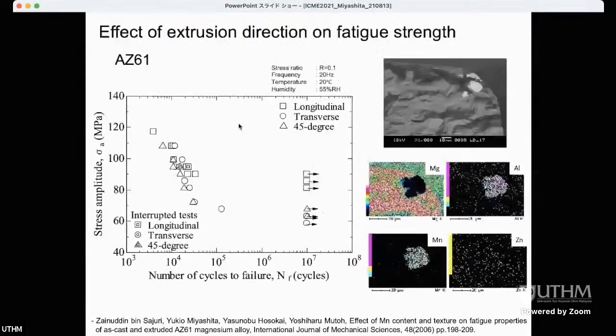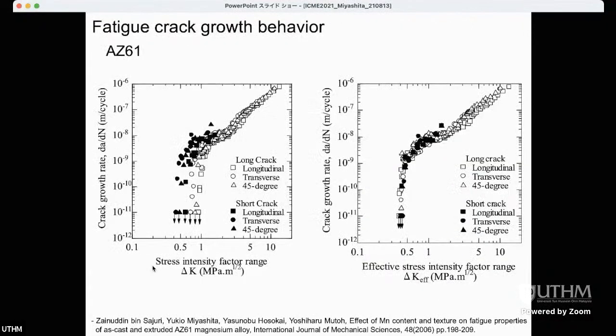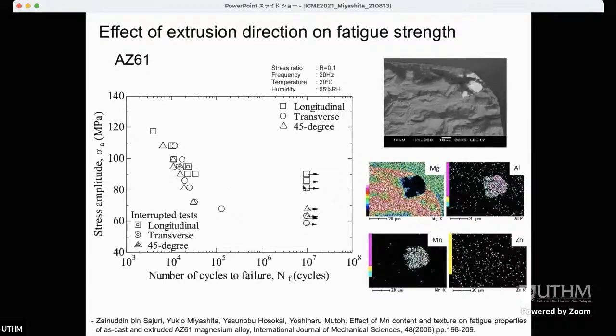So the difference in fatigue strength observed in the fatigue strength test is mainly due to the difference in fatigue crack growth resistance. But when we take into account the crack closure effect, we can get this kind of single line. This fatigue crack growth curve is arranged by the effective stress intensity factor range, which means the crack closure effect is taken into account. So this difference in fatigue crack growth resistance is mainly due to the difference in crack closure behavior in different materials, and that induces a difference in fatigue strength.